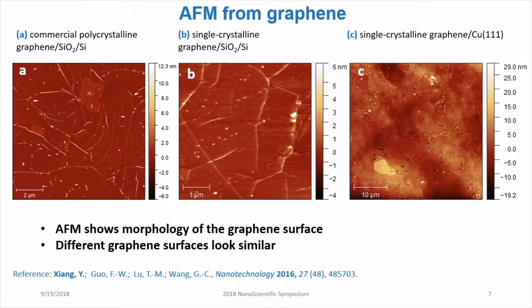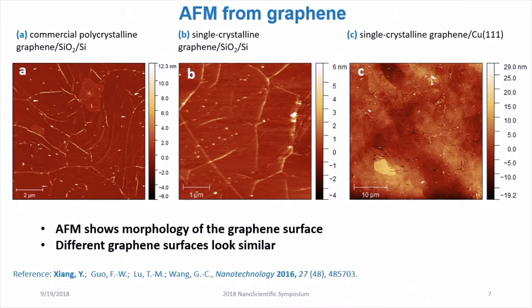The second one is our homegrown single crystalline graphene transferred onto silicon dioxide on a silicon substrate, and the third one is single crystalline graphene as-grown on copper (111). We can clearly see features on those graphene surfaces, such as grain boundaries, wavy features which are graphene wrinkles, and some bilayer graphene islands.